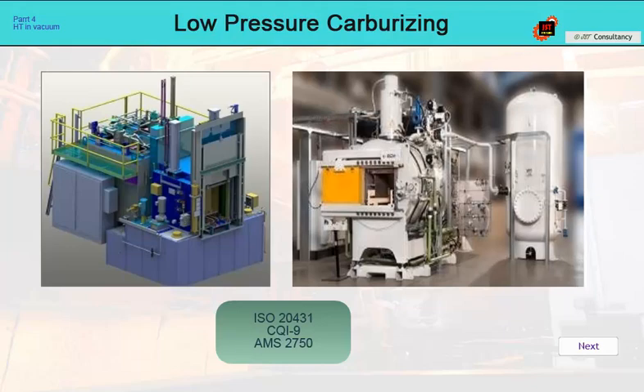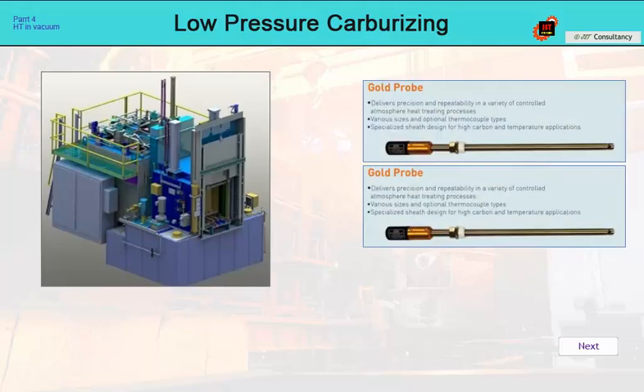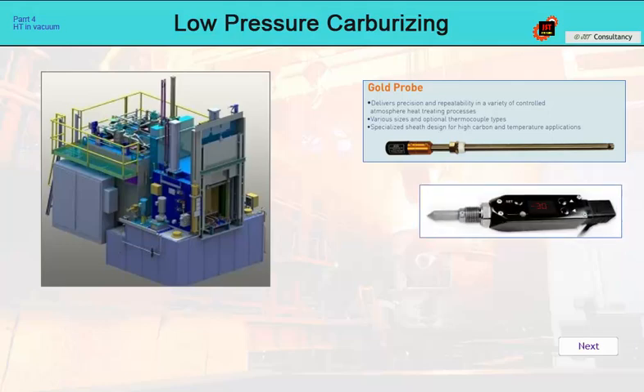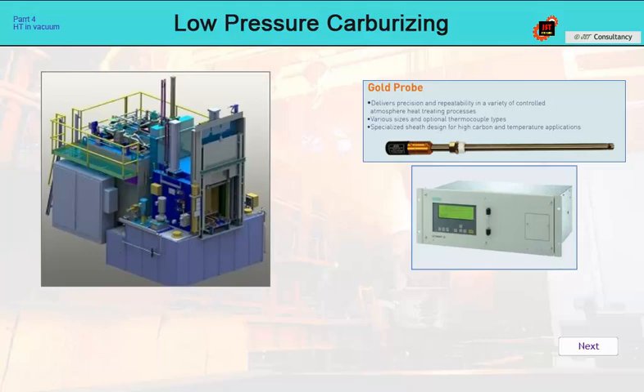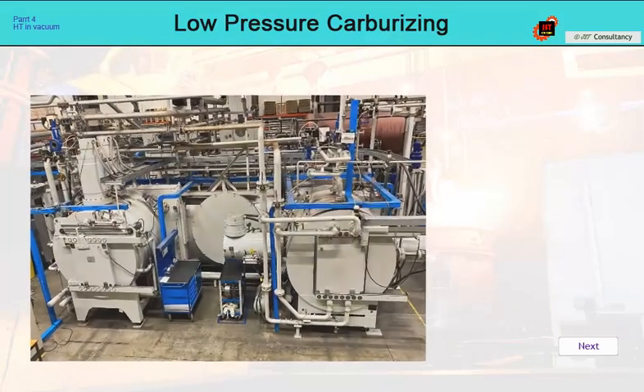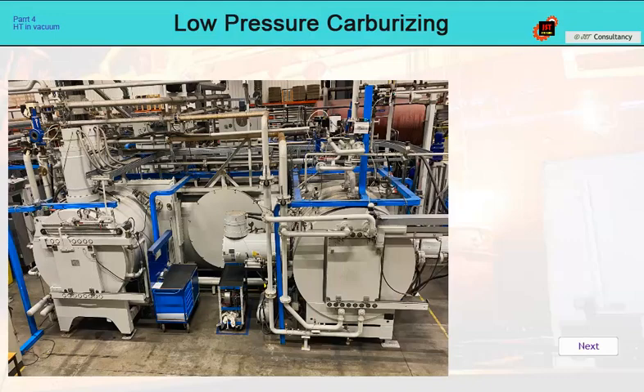In multi-purpose furnaces, we must perform periodic or continuous control of the carbon potential, and these methods must be supervised by a different method. A common combination is 2 parallel oxygen probes, or an oxygen probe and dew point measurement, or an oxygen probe and an infrared analyzer. Measurement of the carbon potential using the foil method is also possible. In any case, the cost of oxygen probes and their calibration is excluded with low-pressure carburizing. The maintenance of equipment for LPC is therefore significantly more economical than that of conventional multi-purpose furnaces.